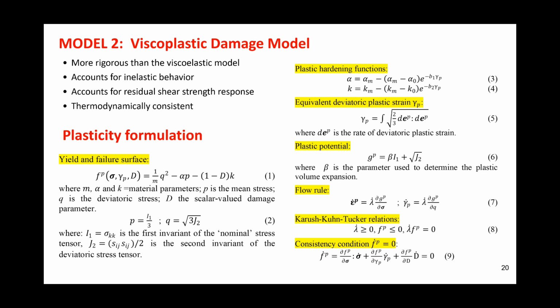We have the flow rule here to get the plastic strain. Just take the gradient of the plastic potential with respect to stress. We have the Karush-Kuhn-Tucker relationship, which says that the plastic multiplier should be greater than or equal to 0. The yield surface should be less than or equal to 0.